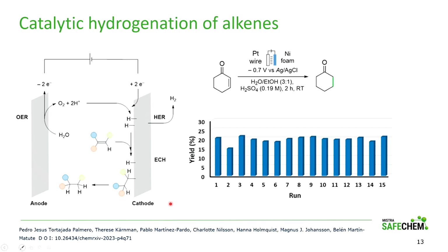Is the catalyst now recyclable? That we did in this study. And what we do here, usually we look at low conversions, because what is very important is to show that the catalyst has the same reaction rate for every run that we test. And indeed, this is what this graph shows. We have a very good and very similar conversion, at least during 15 recycling cycles. So the catalyst is very stable.